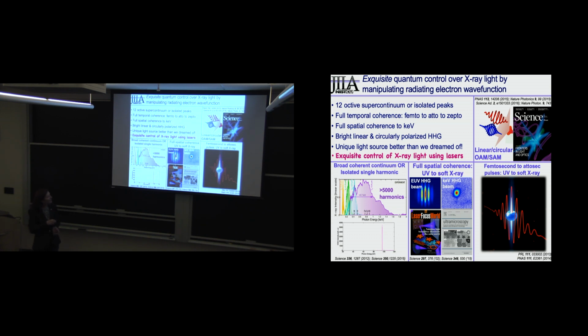There's beautiful spatial coherence, and we can make these ridiculously short pulses, shorter than we thought we'd actually need to look at anything, but these just come out because of the physics. You're only making harmonics while you're ionizing the atom and while it's phase matching. And it turns out those two things shrink the emission to where it's far, far shorter than the laser pulse you're using to make it. And so this is just the physics. We don't get to change that.